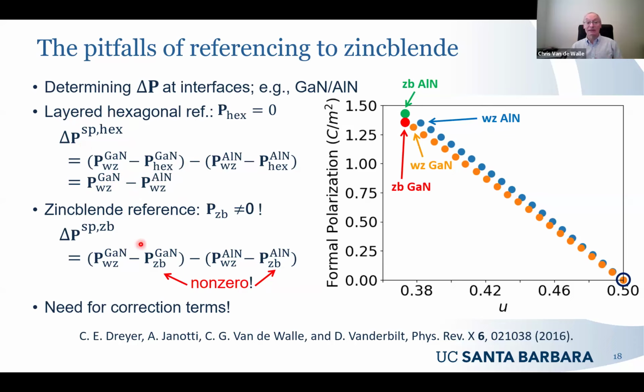In the case of zinc blende reference, we can use the same expression, but we need to take the polarization of our reference structure into account. And these polarizations for zinc blende are non-zero, okay? And as you can see in this plot here, where I've now added in the orange dots the values for gallium nitride, the formal polarization of aluminum nitride and gallium nitride is different for wurtzite, but it actually is also different for the zinc blende structure.